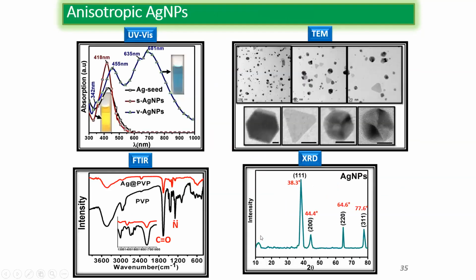So I will show some very interesting research now. As I told, the spherical nanoparticle has very good absorption at 400 nanometers. But as I showed, that is not sufficient. We should have absorption in the broader region. So I made a protocol where I can synthesize all sizes and shapes of the material in one go. There is no need for different synthesis processes; I can just make it in one pot.